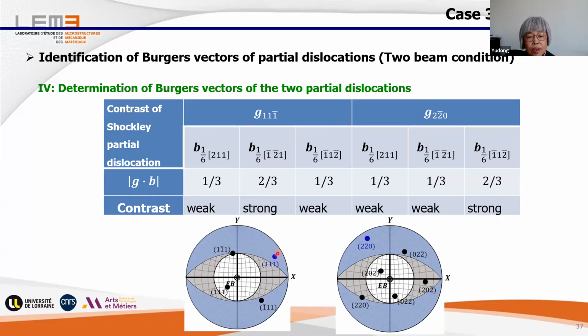And so with the pole figure, we found it is here, and it's exactly in the single alpha tilt zone. And for this 2 -2 0 plane, the pole is here, and so it's exactly in the single alpha tilt zone. And I have to explain a little bit, because here is the beam orientation. So it's normal to the screen.